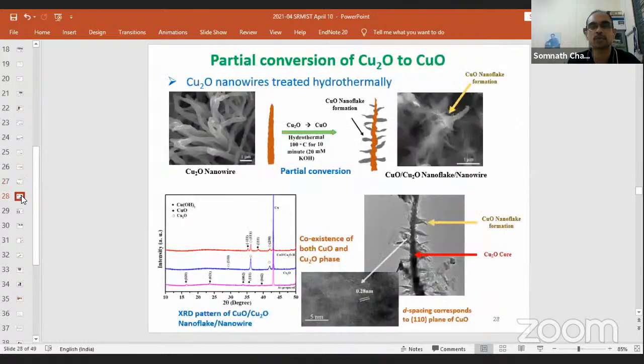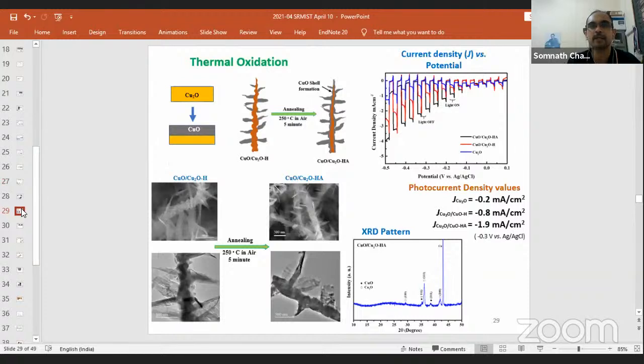So we thought, since we had made this nanostructure, how to make the heterostructure. I will quickly come to this slide. As you can see, we first started with Cu2O. The reason for starting with Cu2O is we did not want a complete oxidation of the nanowire we are preparing. When we have an incomplete oxidation, first we get Cu2O. Then in the second phase of treatment, we treated those Cu2O nanowires, which are in the middle like the stem of a tree, with another step of hydrothermal process. And we found that, beautifully, CuO flakes grow perpendicular to the Cu2O. As you can see in the lower TEM structure, one is this Cu2O, and then the CuO grows like a stem and branch of a tree.